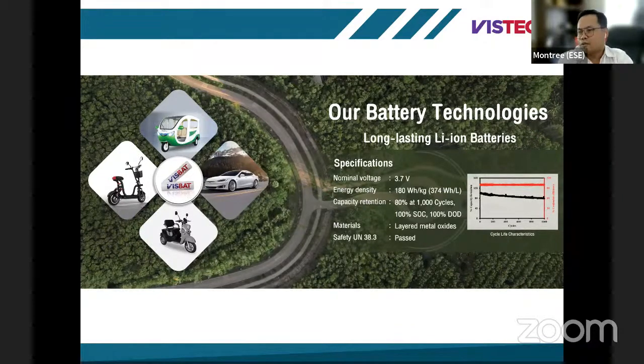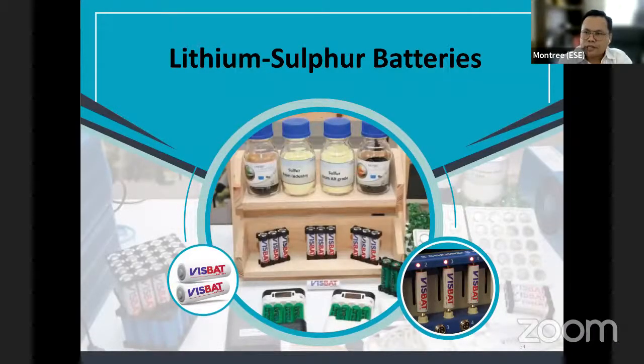LFP can go to really high fast charging, high safety. And right now we can achieve 180 watt hour per kilogram, 40 to 50 watt hour per kilogram higher than LFP, but really stable by using our technologies. And also we have some blue sky research on lithium sulfur battery.